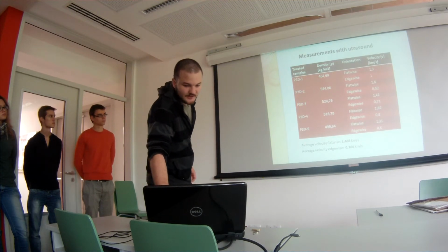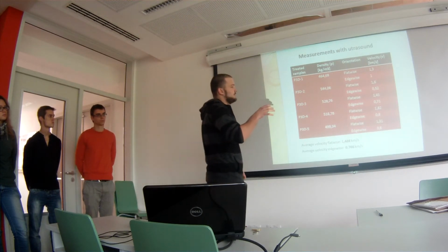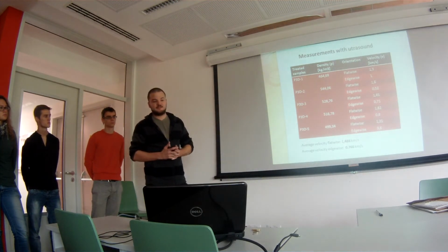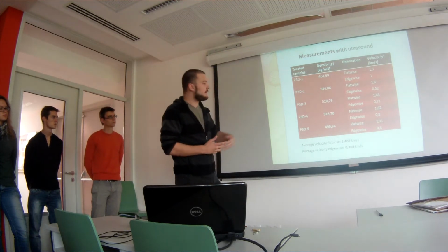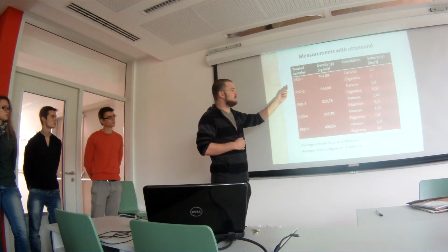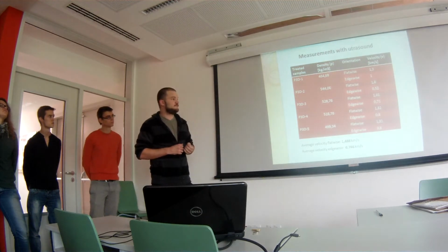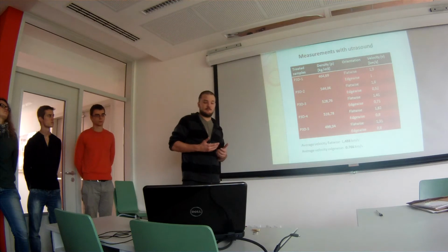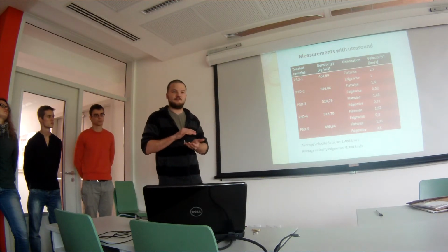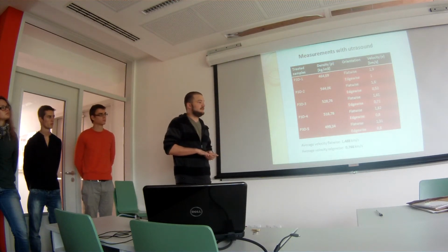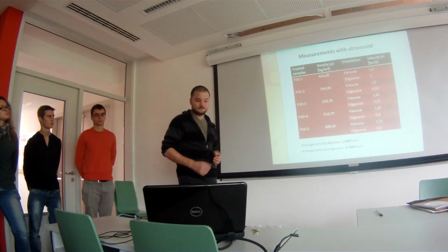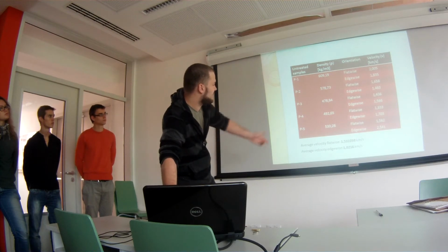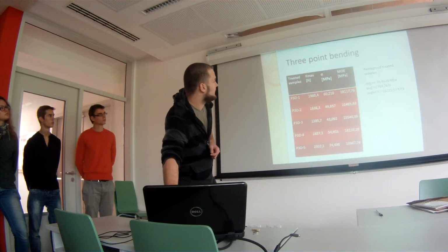In ultrasound, we decided to focus on the velocity because the elasticity results were really unreliable. But you can see clearly from the velocity that in the treated samples, the velocity became much lower. It's probably because there are a lot of cracks in the wood, in the samples, and it made the sound travel much slower. Here, the average is 3.9.